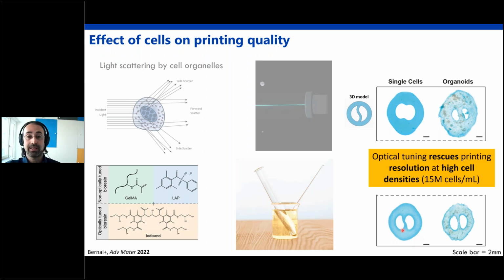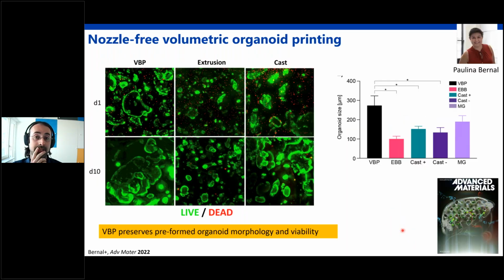So with that sorted, we can see how the technology actually fares when we try to print these fragile liver organoids. And we see that compared to extrusion, as we showed before, most of the cells after printing are shed and they start dying. And the organoids are, of course, smaller in size because we need to pass them through a nozzle, so they get fragmented. And even simple micropipetting is enough to partially damage these cells. Whereas in volumetric printing, we don't have any of these steps. You can just pour the organoid solution into the vials. There is no shear during printing, and therefore we have fewer dead cells, and most importantly, larger and better formed organoids that eventually grow better even during the culture time.